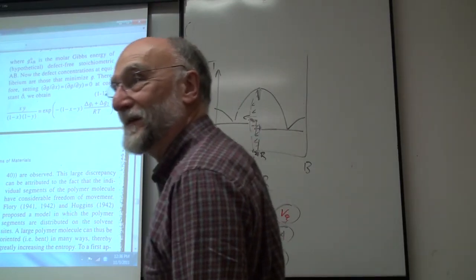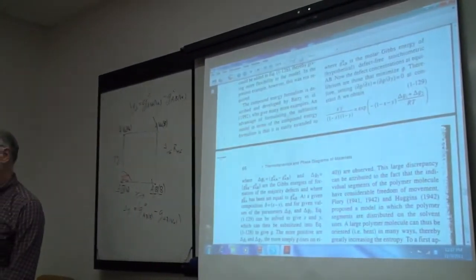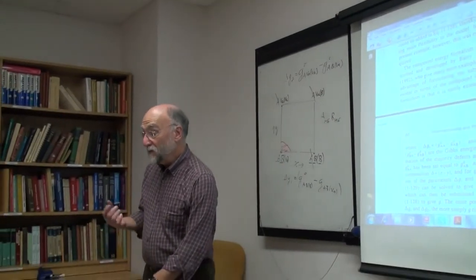So, for example, if you're looking at something that's really useful, the phase diagram's got an awful lot of information in it. And it has the advantage of usually being easier to measure accurately than thermodynamic properties. Measuring enthalpies is really important. The enthalpy of formation of the compounds is very important. If you have the enthalpy of the compound at 298, that tells you an awful lot. The enthalpy of mixing of liquids is also a very important parameter.